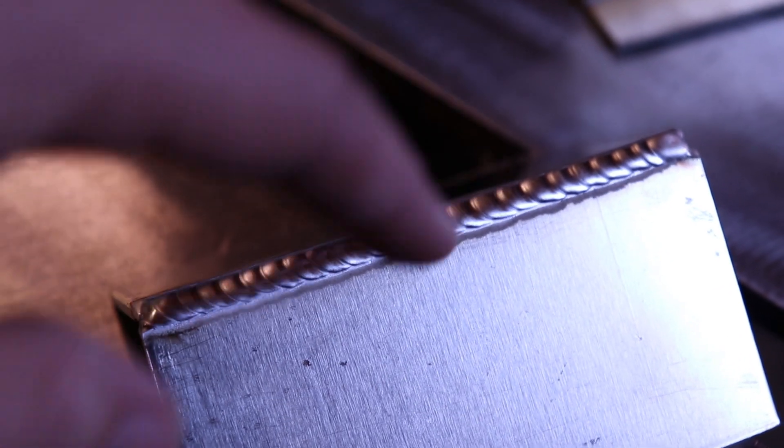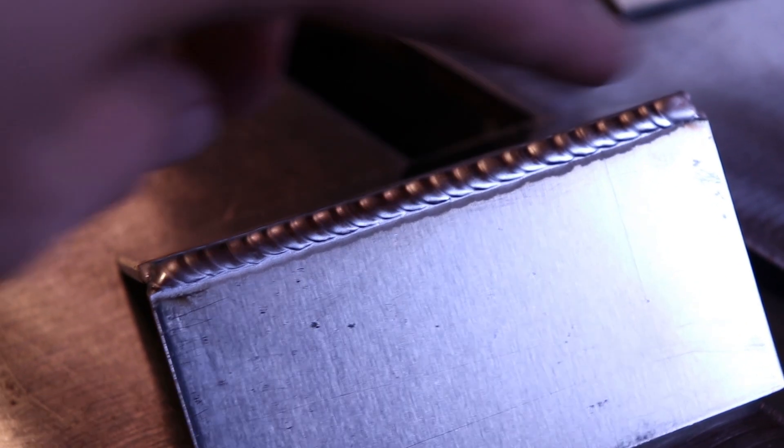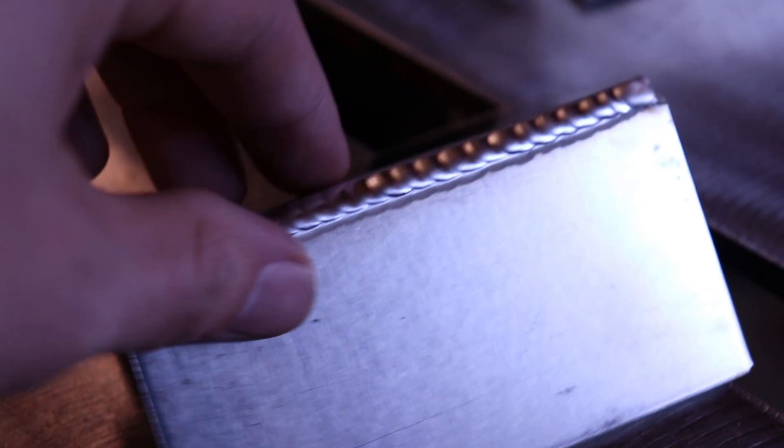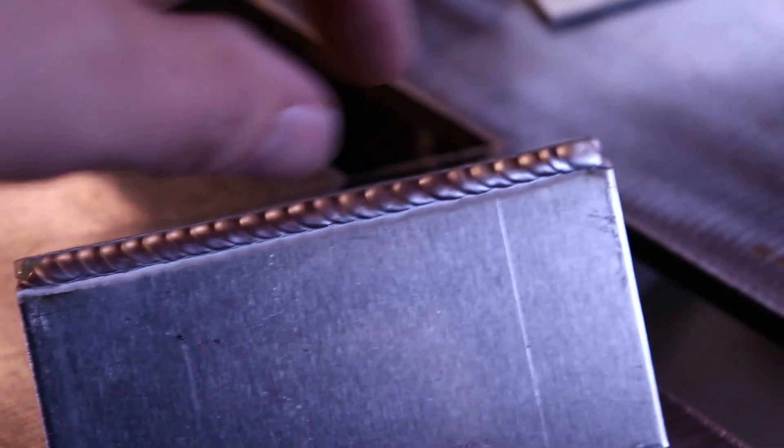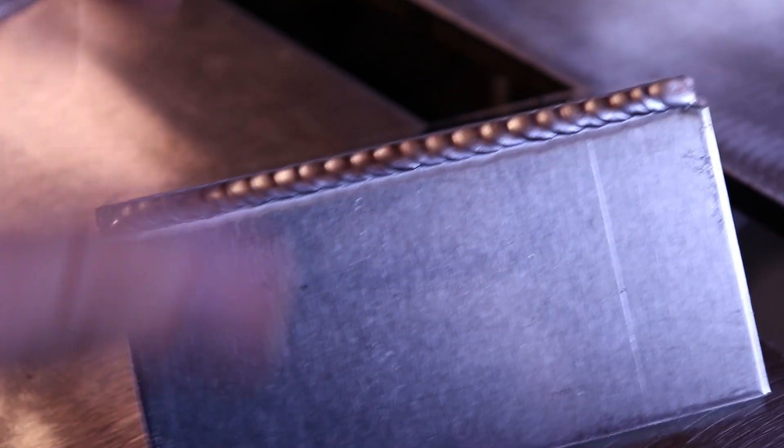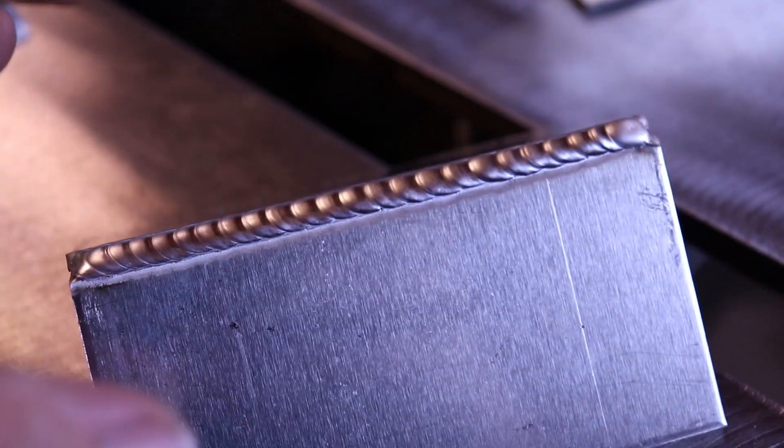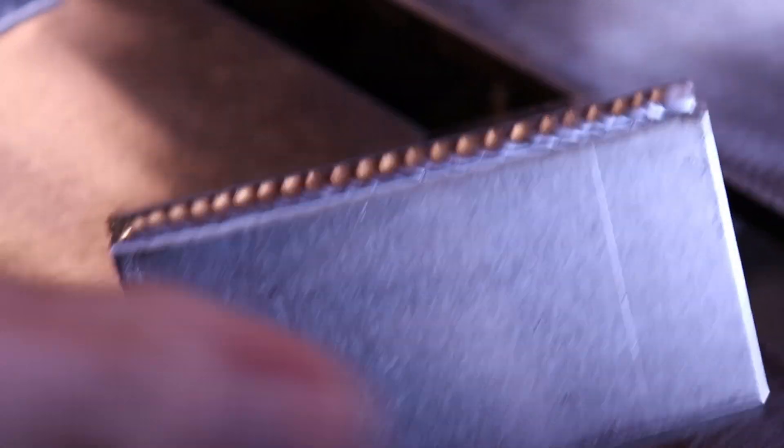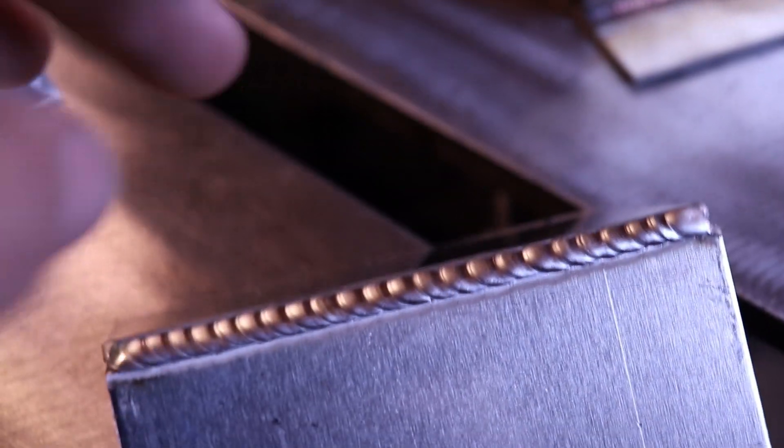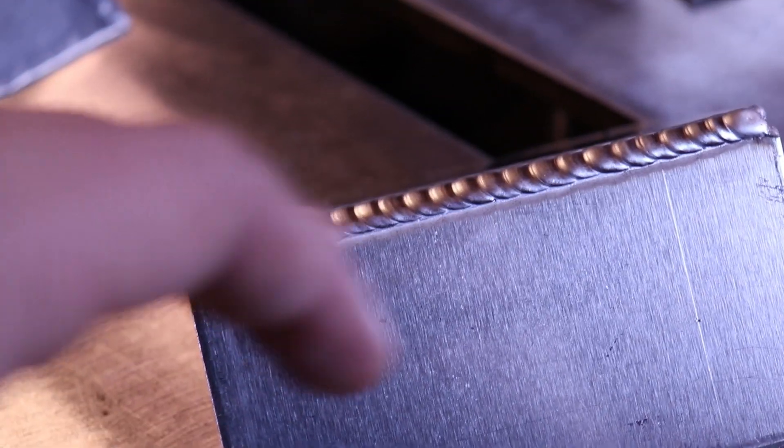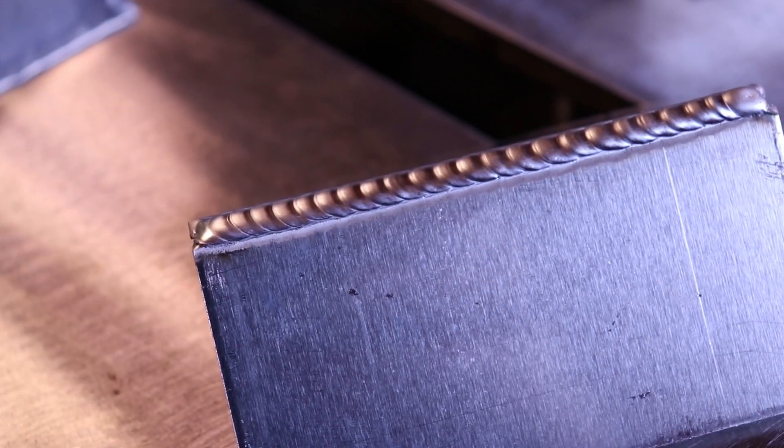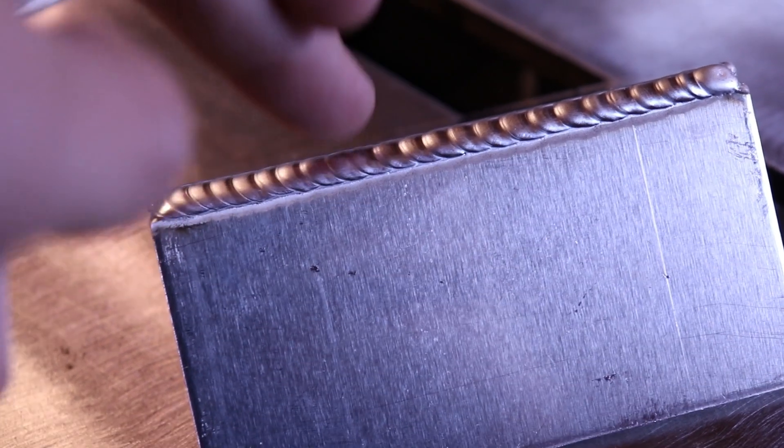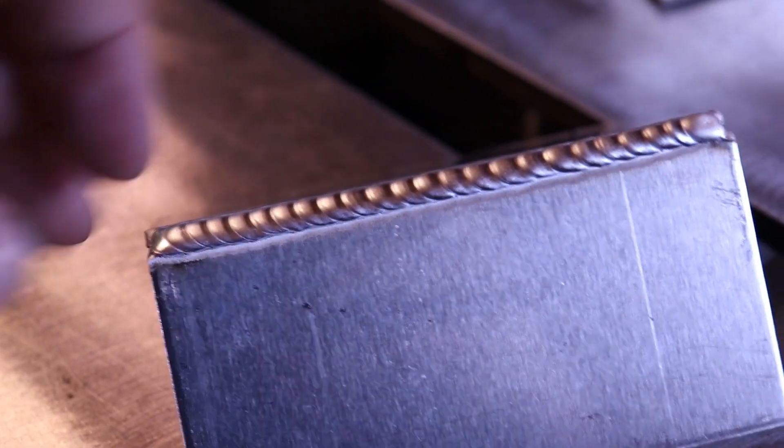So, this is the 1/8 inch aluminum coupon that they have. And I welded it with 3/32 inch 5356 filler. And I used my pulse settings that I found that I really like. I don't use pulse that much but I have been messing around with it. If you're new, I wouldn't use pulse until you have welding like figured out. So, I was using one pulse per second which works good on outside corners because you have to add a little more filler so it gives you a little bit more time. And I was using 70% background and 67% peak time on my pulse. And that's what I came up with.